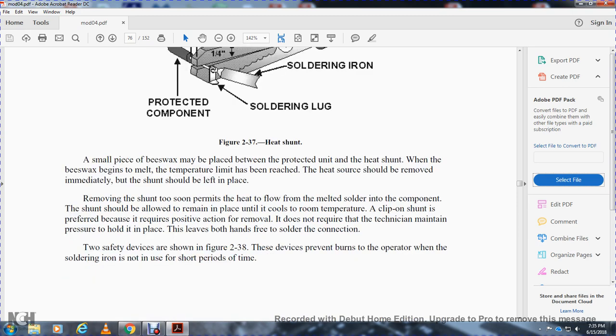Alright, small pieces of beeswax must be placed between the protected unit and the heat shunt. When the beeswax begins to melt, the temperature limit has been reached. The heat source should be removed immediately, and the shunt should be left in place. Removing the shunt too soon permits heat to flow from the melted solder into the component. The shunt should be allowed to remain in place and cool to room temperature.